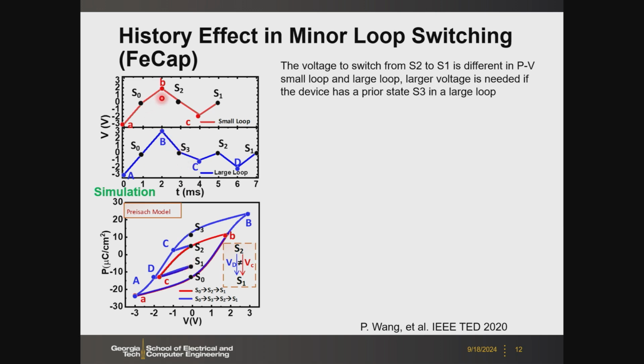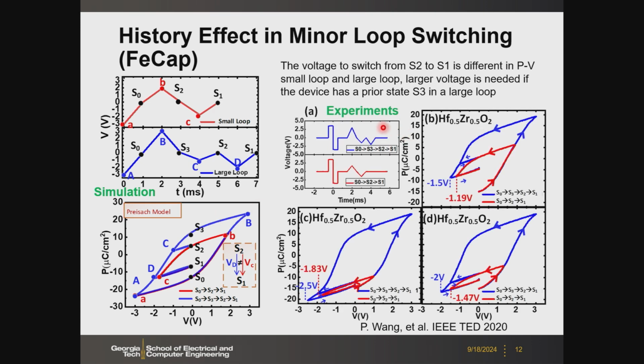And then in the smaller loop, which is the red curve here, we start from S0 and then go to S2, and then from S2 to S1. So here you will notice that for the same transition from S2 to S1, the switching voltages here, VD and VC, are actually different, depending on whether the device has gone through the S3 state or not. So that means there's a history dependency here. So this is simulation, and then we verified that in experiments, first from the FE cap. We tried different trajectories, different combinations, different sweep frequencies, and different sweep polarities. This behavior seems universal.